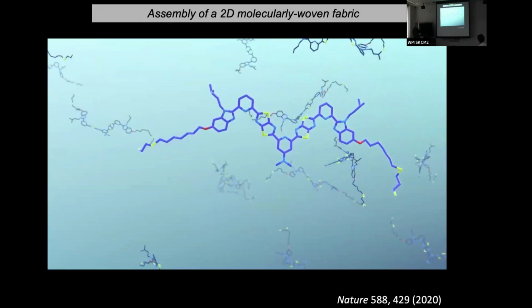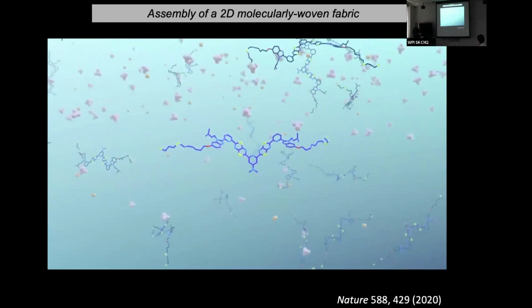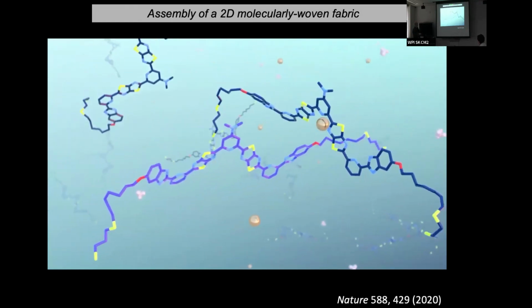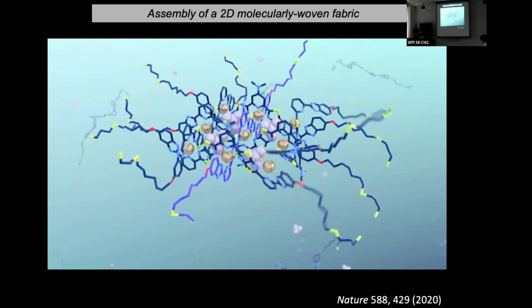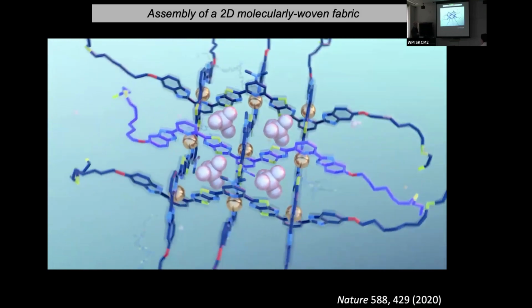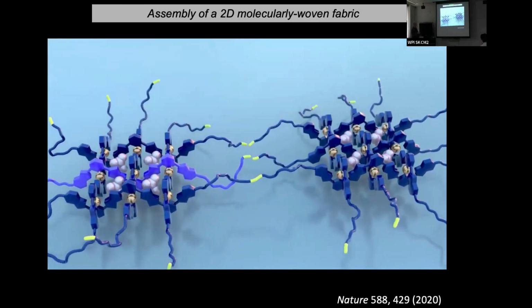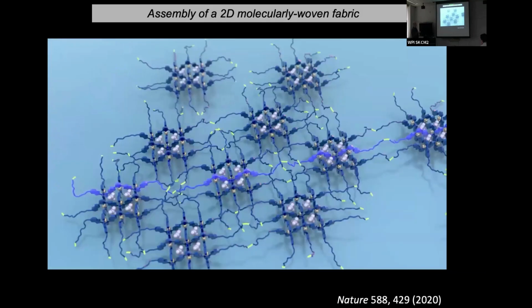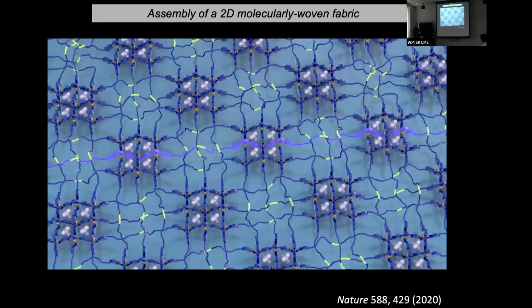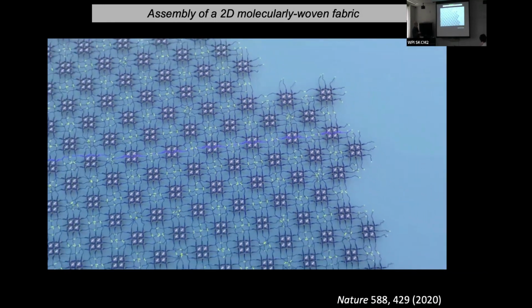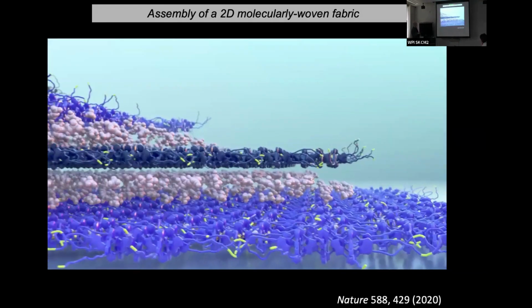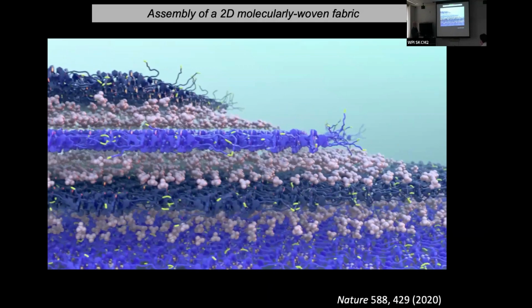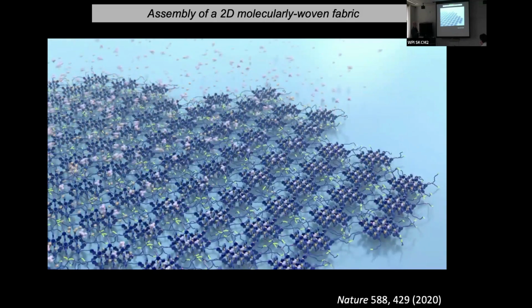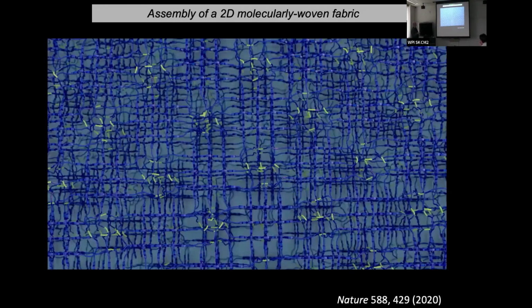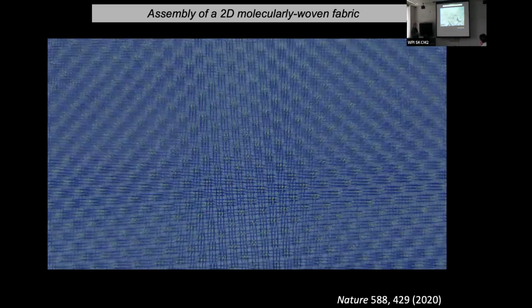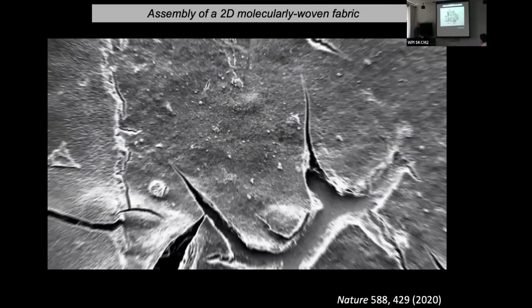And this is a movie of what's actually happening here. So we take the ligand strand, we've got the metals with the BF4 groups present, and those will form grids, with the BF4 groups templating the formation of the 3x3 grid. And then these thiol groups on the end, the grids crystallize, and the disulfide groups are oxidized to connect together to form disulfide linkages. And that forms these extended layers on the surface. And these layered structures are just like the X-ray that we saw before. They've got these layers of anions in between the structures, which stop the polymerization going in 3 dimensions. They're just in 2-dimensional layers. We then remove the metal ions and the anions by treating them with cyanide. And then this wholly organic woven polymer has this layered structure.